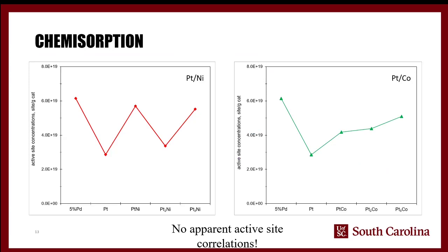We've tried using some chemisorption techniques here to see if a certain ratio of the two metals will provide more active sites just based on, say, how the particle forms. And what both of these show is that there's really not any correlation between the ratio of the metals for either nickel or cobalt and the apparent active sites. And so that sort of throws out one of the potential explanations, which is basically, at this certain ratio, you have more active sites, therefore it obviously should be more active. That's not the case here. So we sort of eliminated that argument for ourselves.